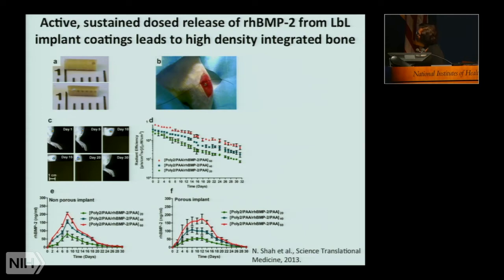We looked at different loadings. 20, 40, and 60 layers are representative of these three different loadings. And we look at the concentration of BMP2 that is accumulated in this area of interest, which is shown here, by excavating the tissue and determining how much BMP2 is there. And what's interesting is the numbers here.